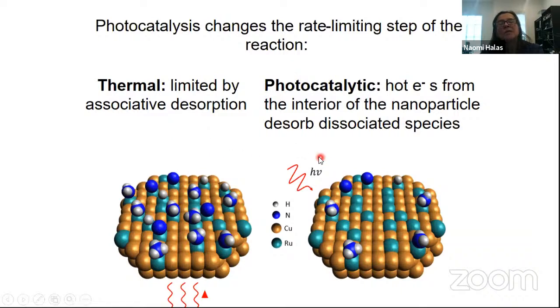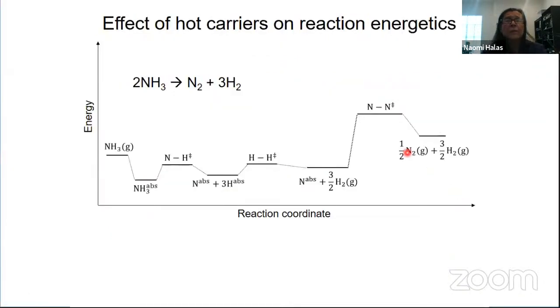But it turns out that when we do the same reaction with light, we have a new mechanism. And I've alluded to this a few minutes ago, that we actually can do desorption. The electrons inside the metal, when you excite the plasmon, will desorb the actual adsorbates. So they lower the barrier to that particular desorption step. And since they lower that energy, they keep the surface clean. And so we have more and more sites available for ammonia to now come on and adsorb onto the surface. So let's see what that looks like. If we look at the effect of carriers on reaction energetics, then we actually see here's the rate limiting step that we saw earlier.